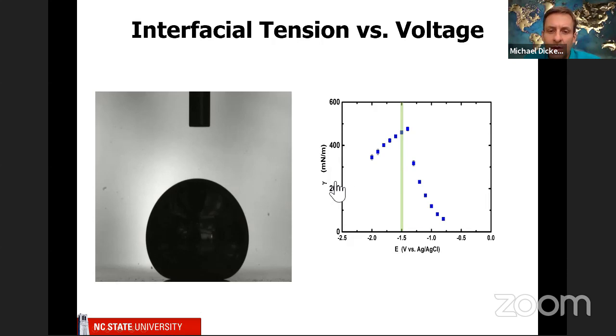And here at this high surface tension state, the surface tension is about 500. Remember, if you're not used to these units, the surface tension of water is down here around 70. So this is a huge surface tension. And I apologize, this is an inconvenience of electrochemistry, but this is at the so-called open circuit voltage. That means we're not applying a voltage. So even though it says negative 1.5, this is just what Mother Nature gives us when we stick the electrodes into the solution. Now, when I hit go, we're going to start applying a potential.